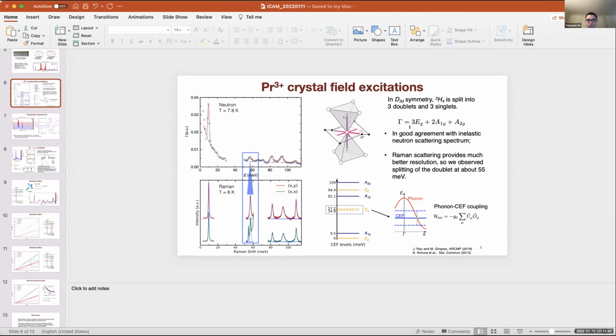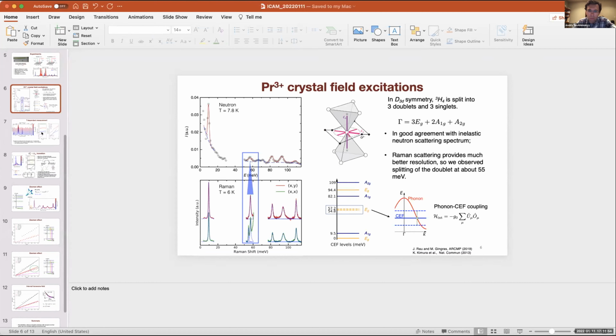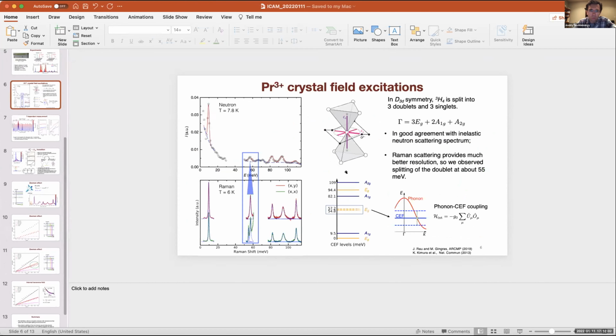Yeah. Okay. And then the next related question is that presumably in order to see anything in Raman, the optical transition will have to be allowed, going, let's say, from Eg to a high-lying singlet, right? So that means you must have done the crystal field analysis and you know what the MJ components are of each of those states. Yes. So for instance, hypothetically, imagine a singlet was in an MJ equals 0 state, but your non-Kramers doublet is primarily, you said, MJ equal 2, right? So then optically, this wouldn't be an allowed dipole transition. The fact that you see it presumably means it's allowed, correct? Right, it's not a dipole allowed transition.